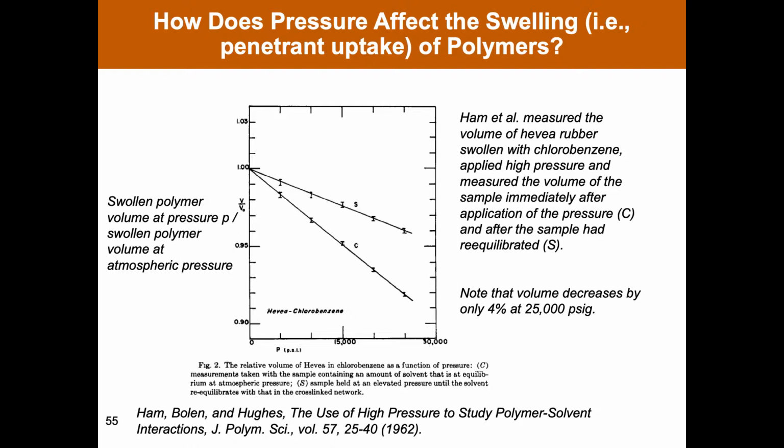I have no idea why they were doing this, but they were taking samples of rubber and swelling them in organic solvents. And then with the rubber surrounded by solvent, they were pressurizing the solvent and monitoring the change in the volume of the swollen rubber, as a means of monitoring whether the concentration of solvent inside the polymer increased or decreased as the pressure of the solvent went up.